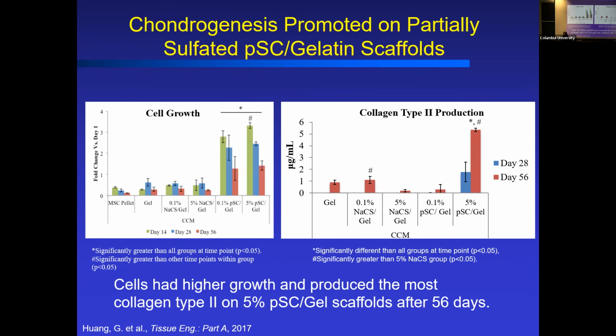So we look more carefully as well. We start to look at different amounts of sulfation in the cellulose and incorporate that into the fibers. What we found, interestingly, is that if you use a partially sulfated form of that cellulose, we see high amounts of growth in comparison to, say, scaffolds that contain the fully sulfated cellulose. Shown here in those bars are numbers of cells, fold change in numbers of cells over time. And that's quite interesting. Again, for those defects where we want to promote growth of cells as well as differentiation, eventually that may be an important composition to use. It also will give you collagen type 2 production.